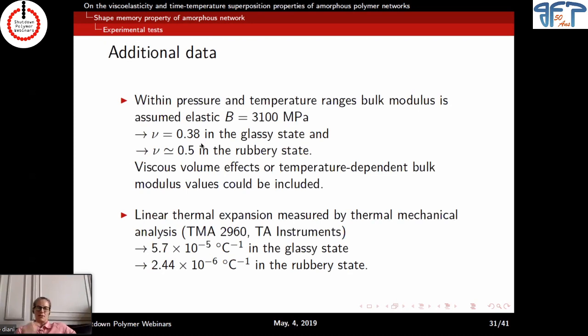Okay, so that's very basic. You just do a uniaxial tension, for example, in the glassy state at cold temperature. By a uniaxial tension test and looking at the ratio of the transverse strain over the longitudinal strain, you get the Poisson ratio. What's very difficult is in the rubbery state. We looked at the two free faces of our sample and look at the change of volume upon uniaxial tension.